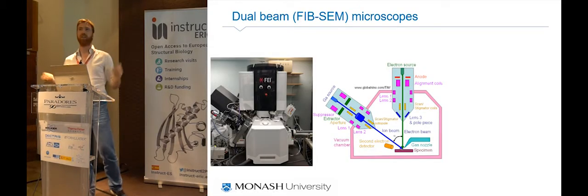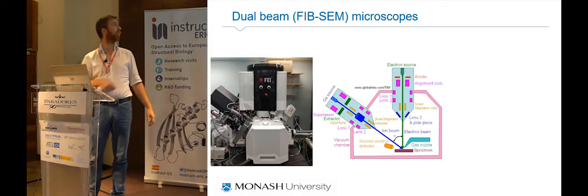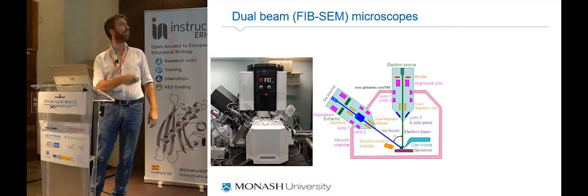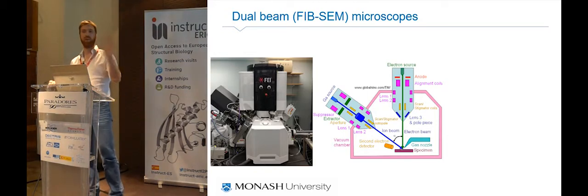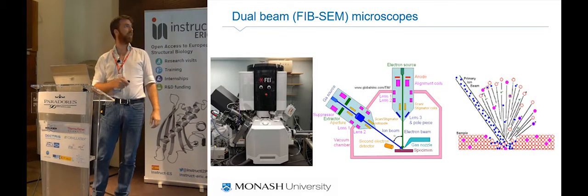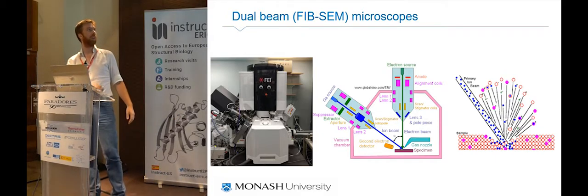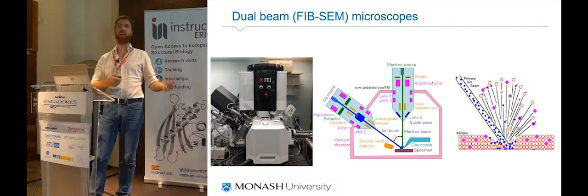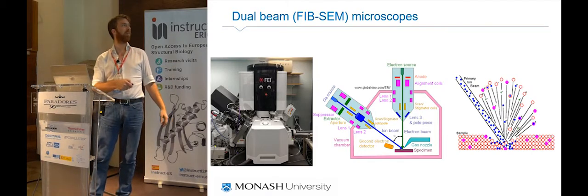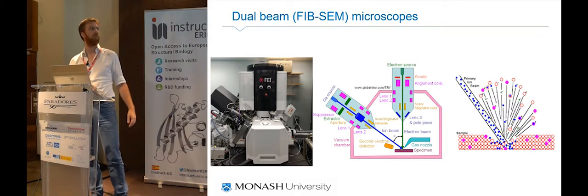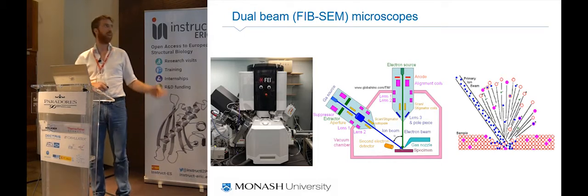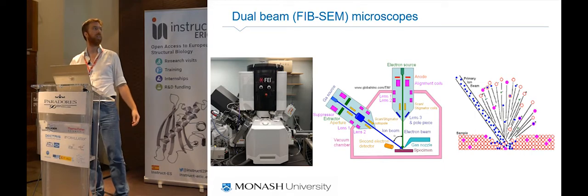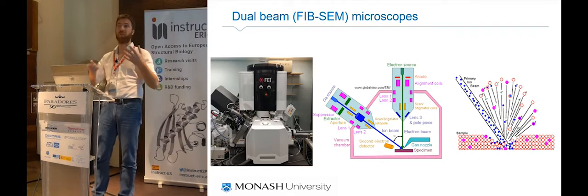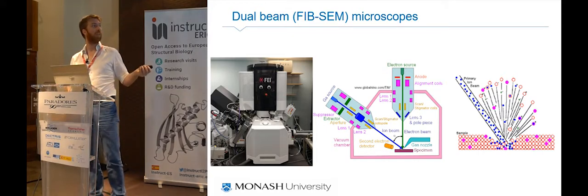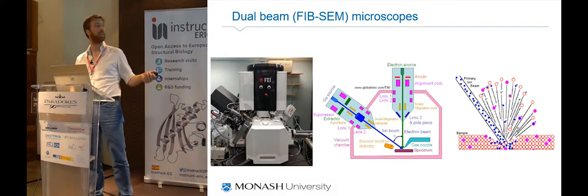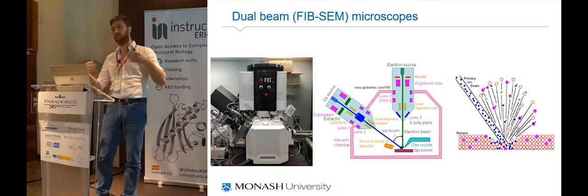If anybody hasn't seen a dual beam before, this is how it looks, at least one of the ones that we had at Monash. You have an electron column which is top down, and then anywhere between 38 and 90 degrees you can have a focus ion beam. The focus ion beam is a flux of ions which are accelerated and collide onto a sample, and upon collision you're sputtering away the atoms which form the sample. With the atoms you're going to have generation of secondary electrons as well as secondary ions. These can be used for imaging, so you can see what you're sputtering. Another thing that will happen, which is pretty important, especially in the context of material science, is that the primary ions from the beam will be implanted into the material.